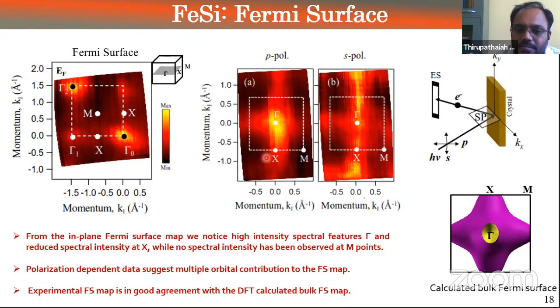So this is how it looks. This was measured with p polarized light, and this was measured with s polarized light, to see the orbital contribution. And in fact, you see that there is a change in spectral intensity, which confirms that these Fermi surfaces are contributed by multiple orbitals. And here is the definition of what is p polarized and s polarized. So this is your electric field oscillation, this is your sample surface, this is your scattering plane, and this is the entrance slit of the analyzer. So with respect to your scattering plane, we in general define what is p polarized light and s polarized light.